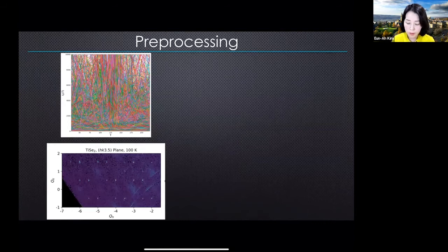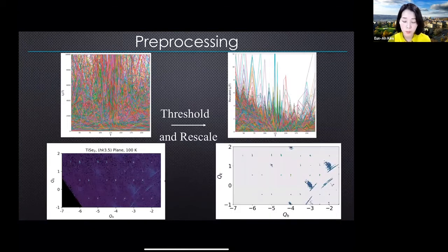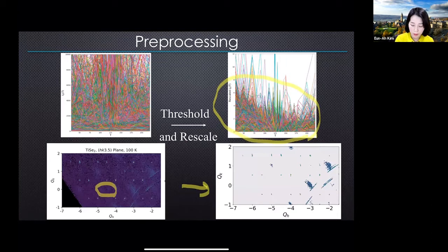So we developed a pre-processing scheme. It's really my student Jordan who came up with the idea of how to pre-process. And with a principled approach, he was able to figure out how to process this data and reduce it down to the data set that has a meaningful temperature dependence. Now, when we threshold and rescale, thresholding means to separate out the data from the noise, and it means the volume of the reciprocal space to be investigated has also shrunk. So now we're not going to investigate this vast empty space, because X-ray data is rather sparse. We're just going to focus our attention on the selected set.